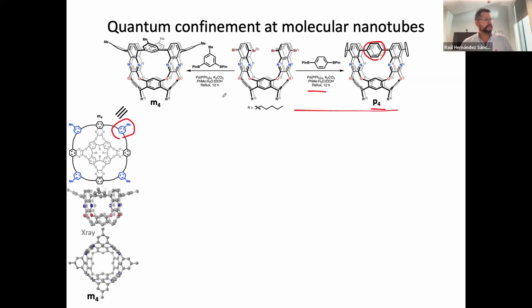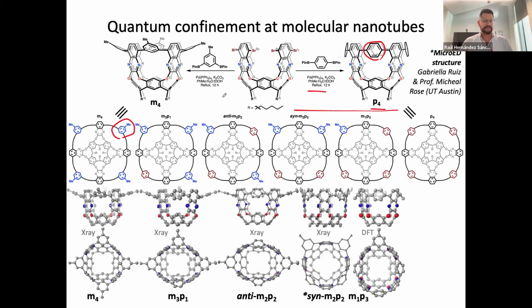They were able to obtain the crystal structure of that compound, so M4, and also all of the intermediates in between those two bookends, the P4 and the M4. All of those isomers are shown here. We have crystal structures, except for one that we have a lot of trouble getting. But for what it matters, the NMR is pretty indicative.